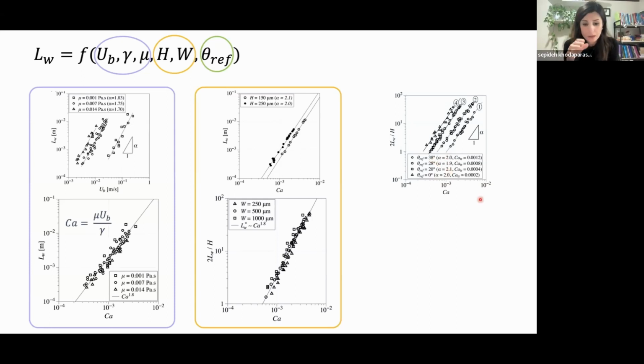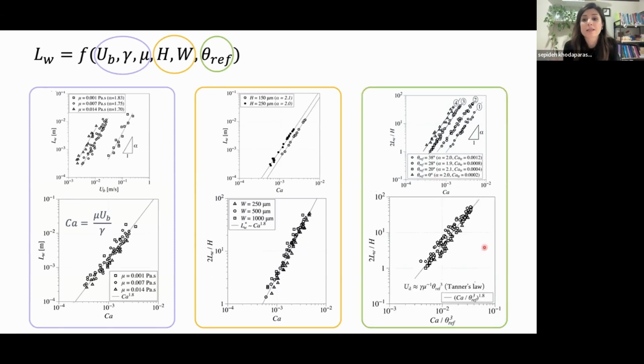And in dry out patches, the growth of the contact line motion in dry out problems, we know that the speed of the dry out front scales, for small wetting angles, with the angle to the power 3. So it means that the speed that we have in the capillary number here needs to be corrected and account for this dry out contact line motion.